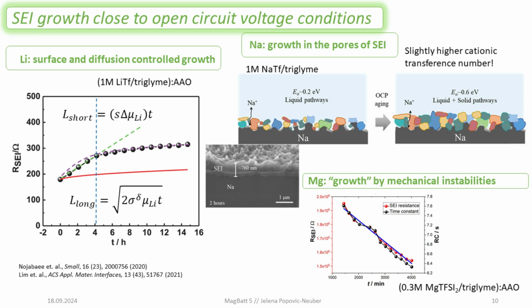So, okay, if we look at what we have seen with this kind of impedance spectroscopy analysis, the most interesting part is indeed this, that we see in the case of sodium with triflate and triglyme electrolytes, liquid pathways at the very beginning when we assemble the cell. So this is how the FIB-SEM looks like. But then after long-term aging, this is 600 hours, we still see that the activation energy is around 0.6. So it means it has not densified yet. We are still far away from the lithium case, in particular in the carbonate electrolytes. So there are still some liquid pathways.